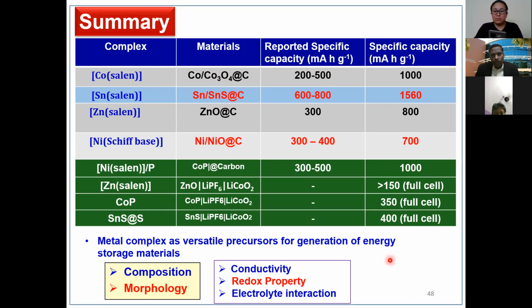What we did was we changed the composition, morphology, conductivity, and redox property. By doing so, you get much better electrolyte interaction that facilitates the redox reaction, either conversion or reconversion reaction, and it enables the storage of lithium or sodium.